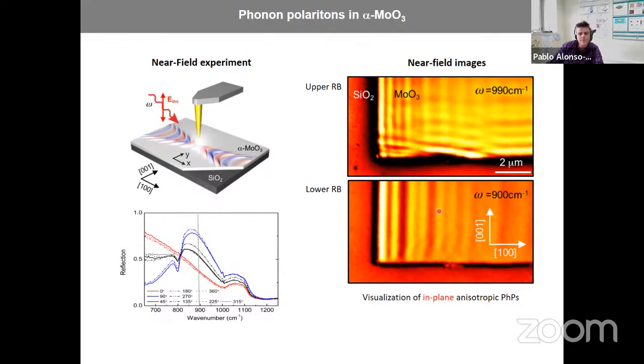And here we saw this striking image where there were no fringes in this direction, but there were only fringes in this other direction. So this indicated that in the plane, because we are looking here at the polaritons in the plane in this material, there are some frequencies where they are highly anisotropic. They propagate in certain directions only. But what directions are they propagating to?